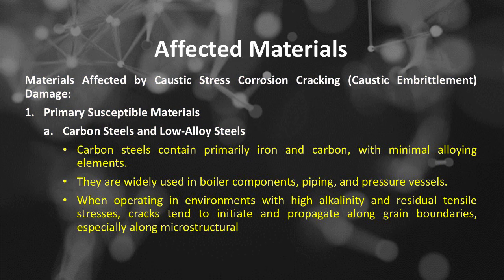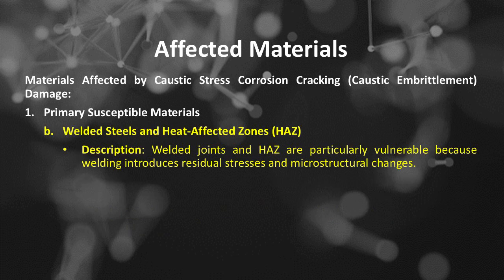Carbon steels contain primarily iron and carbon, with minimal alloying elements. They are widely used in boiler components, piping, and pressure vessels. When operating in environments with high alkalinity and residual tensile stresses, cracks tend to initiate and propagate along grain boundaries, especially along microstructural features. Number B, welded steels and heat-affected zones. Welded joints and HAZ are particularly vulnerable because welding introduces residual stresses and microstructural changes.